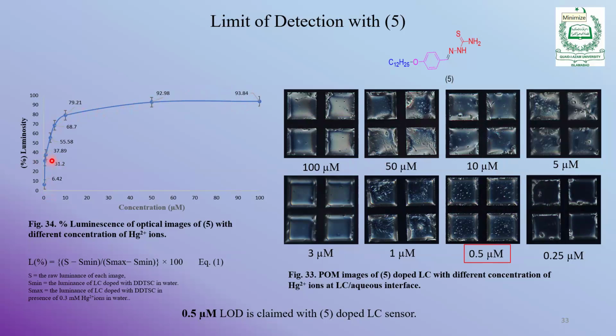And this is the benchmark value of luminescence. Below this, our eyes cannot see the luminosity. We cannot detect any change. So 30% luminosity should be obtained. 30% luminosity is obtained with 0.5 micromolar. So it means that with the 0.5 micromolar solution of amphiphile ligand, you can detect some change. If you decrease further, any change will not be detected by your eye.